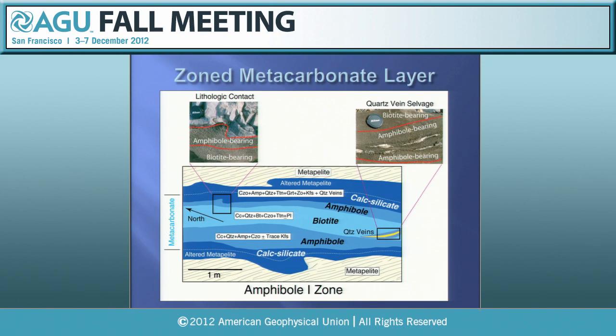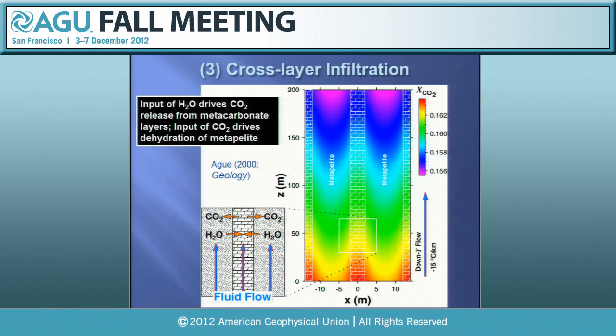And you can model various flow reaction scenarios, which we've done here in terms of coupled fluid flow and chemical reaction. We've shown the layers of metacarbonate as vertical. You could imagine isoclinally folded strata. The actual orientation of the layers doesn't mean a whole lot here. What's going on is the whole system is heating up. Fluid is moving down temperature. And what's contoured here are XCO2 values. They're higher in general at higher temperatures and lower at lower temperatures, which accounts for the overall color trend.